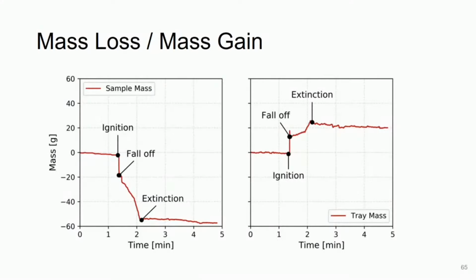During our experiments, we also, as I've mentioned, continuously monitored the amount of mass lost from the experimental sample and the amount of mass gained by the debris tray that was situated below the sample. These data are shown here, mass lost on the left-hand side and mass gained on the right-hand side. And by comparing the mass of the sample with the visual observations, we observed a sudden decrease in the sample mass at 1 minute and 22 seconds, and this occurred when the front plate of aluminium fell from the specimen. The recorded decrease of sample mass corresponds with the expected mass of the aluminium facer plate.